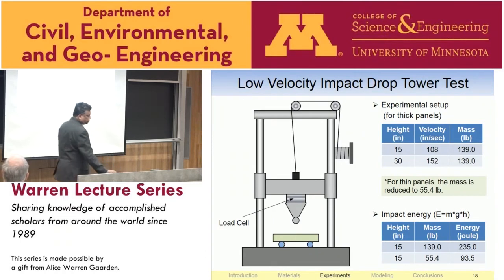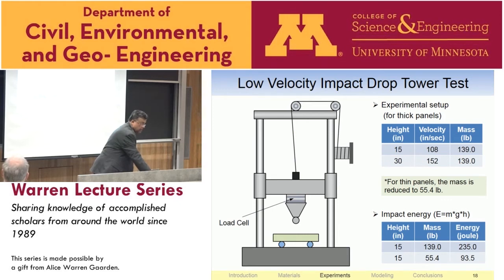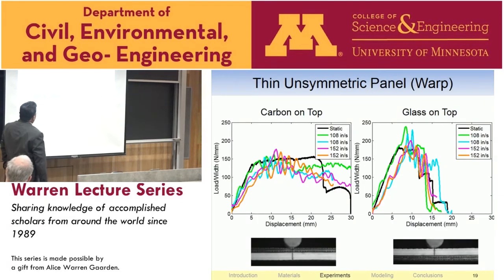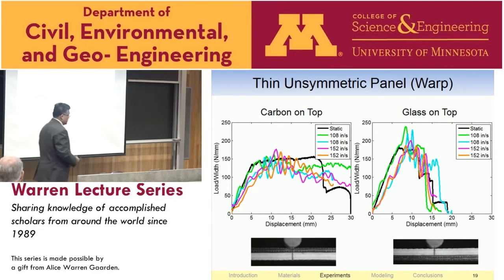We also did some drop weight tests using a drop tower under the same configuration, double rollers to make it not rebound. Now, some of these results are filtered. The high frequency noise is taken off. You can see that as a function of the loading, you see different behavior. But if the carbon layers are on top, you get a lot of ductility, so-called ductility. But if the glass is on top, you get abrupt failure. So microstructure will influence how your structure is going to behave, and they may not be the same when you change your loading rate.